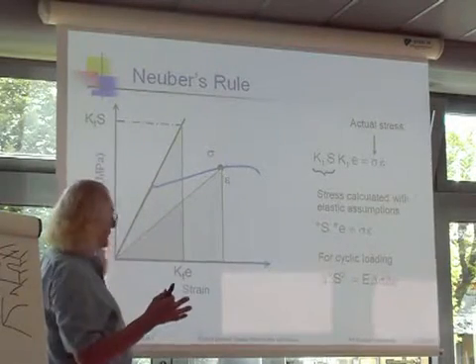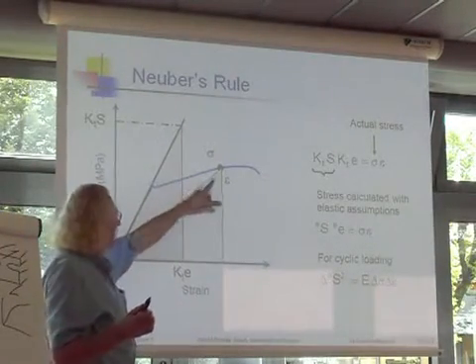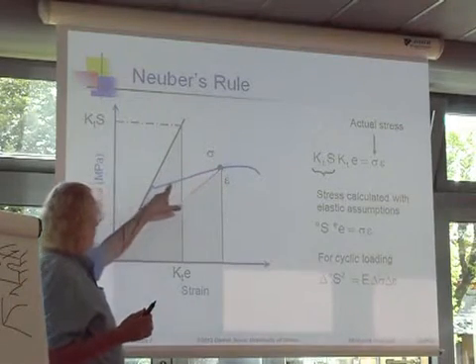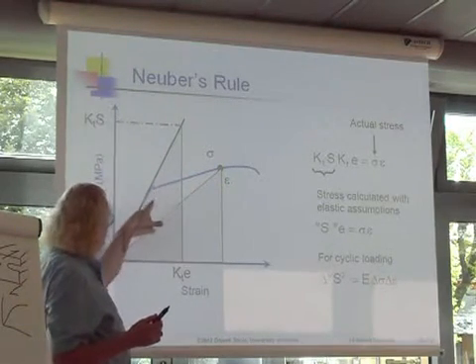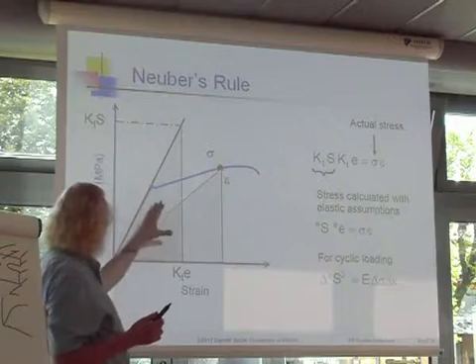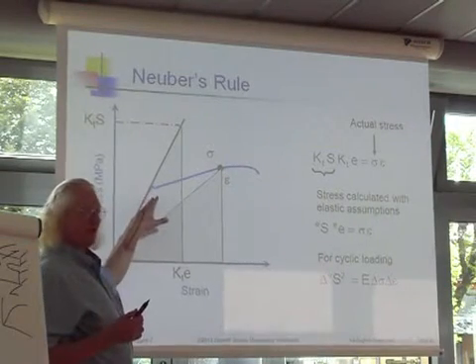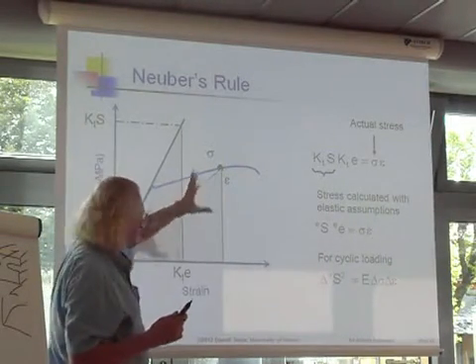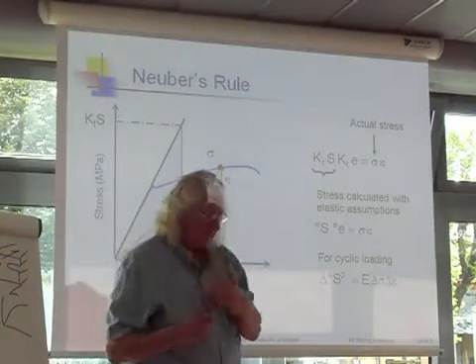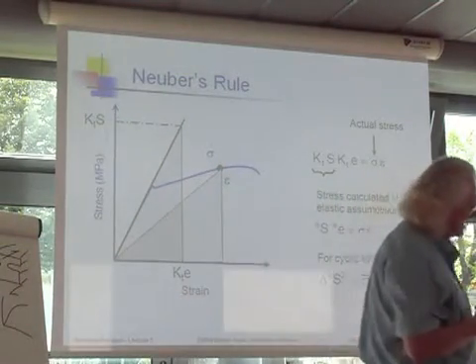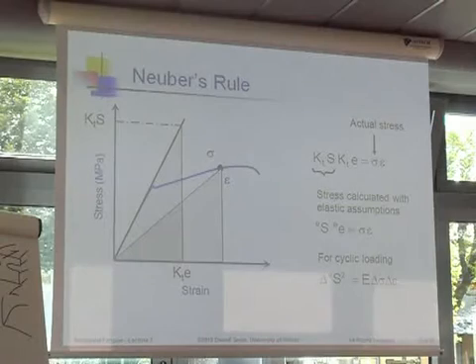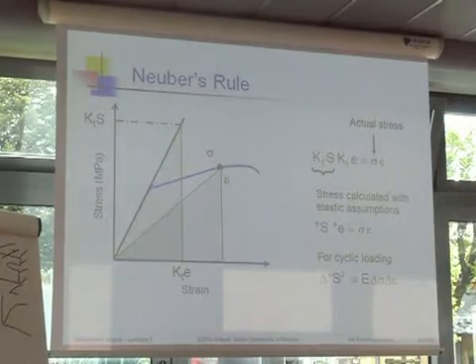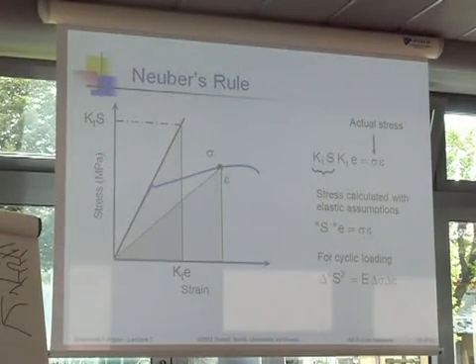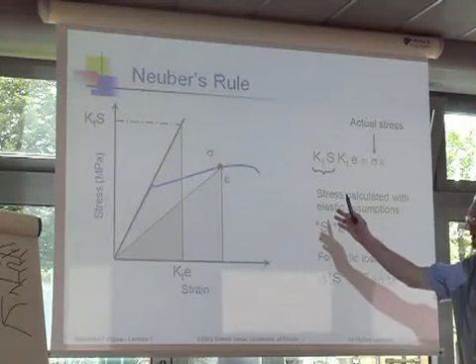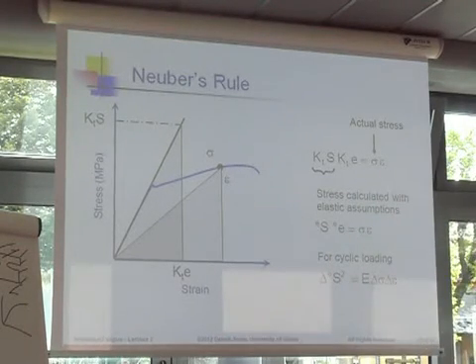And of course, for this, I've exaggerated this a lot. The normal plastic strains we deal with are way down here, and so using this method you get a very good approximation of the energy that's under the stress strain curve. And so that's why it works. And people have been using that for uniaxial fatigue for the last, I don't know, 30 or 40 years. There are some other rules where people actually calculate the strain energy and they worry about the shape of the stress strain curve and so on. It gives a slightly